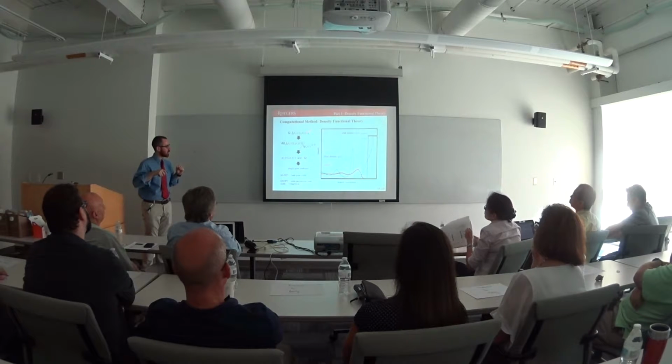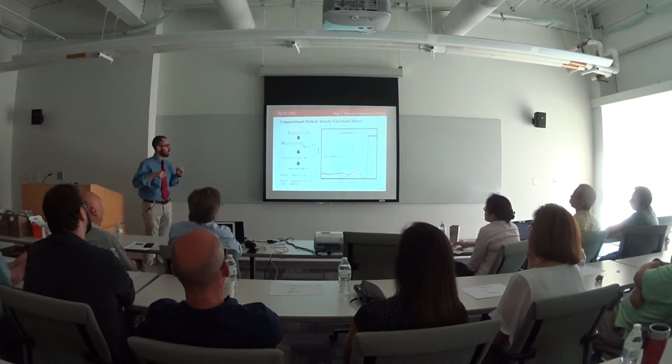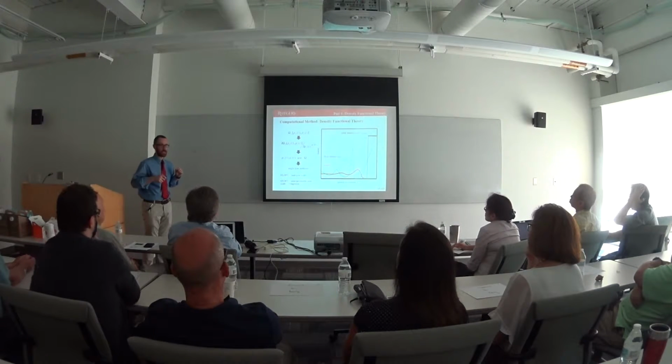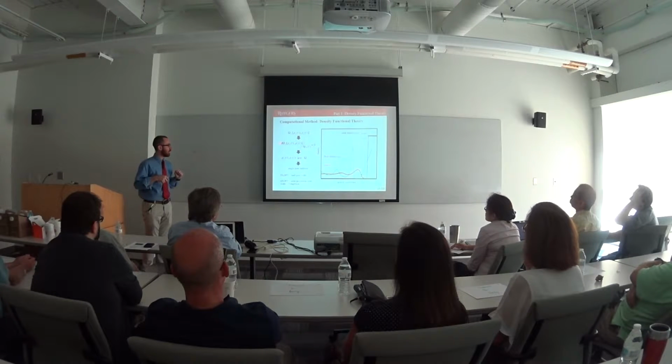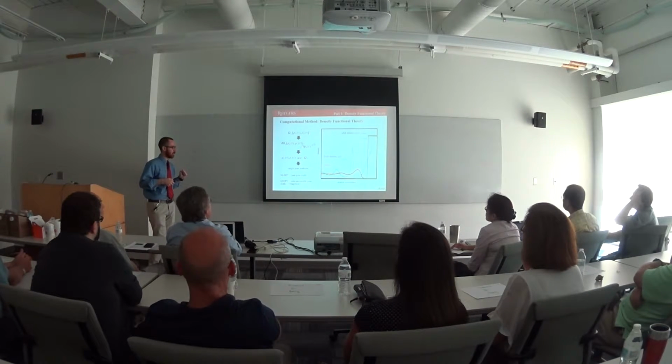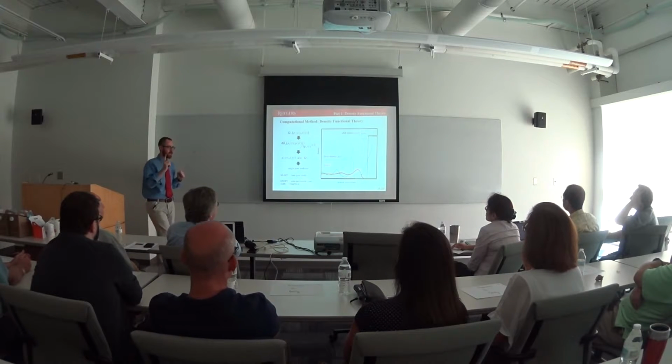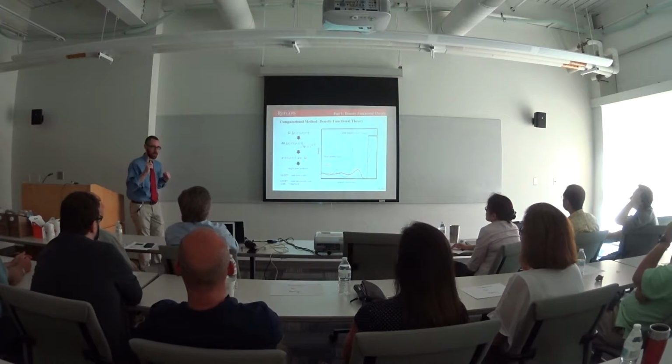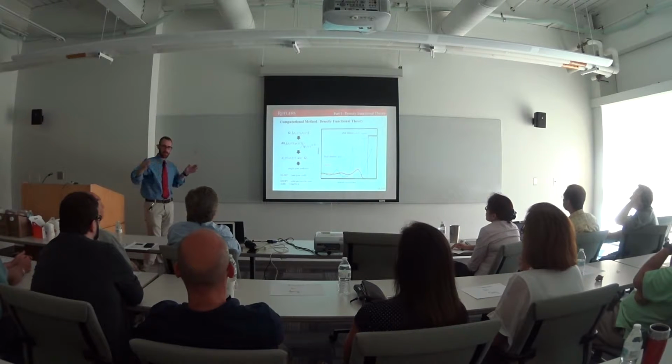This is accomplished by minimizing our grand potential, which is a function of the fluid and the solid density across your pore. We take the first derivative in the fluid density, set it equal to 0, and we get our equilibrium density profiles. We have to do this once for every pressure at which we wish to do a calculation, and so we have to string together a bunch of these calculations to get one adsorption isotherm.